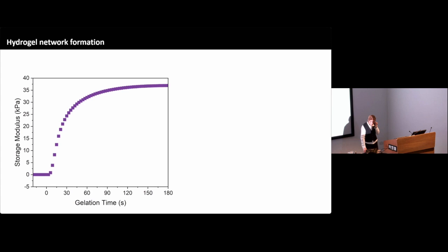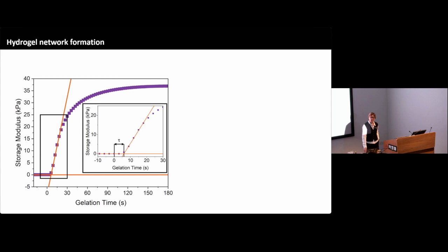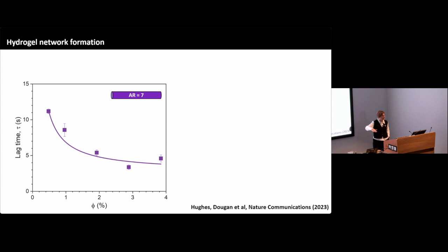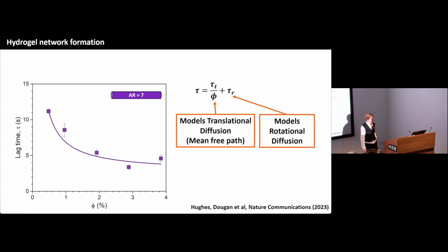And so I'll have to skip over the details, but we did some rheology experiments to measure the storage modulus with time. We measured the lag time, which is defined as the time it takes for gelation to occur. We did this for all of our different constructs and measured the lag time as a function of volume fraction or concentration of our building block in the system. And if you think about that lag time, it's related to how that object is moving around as it tries to form these connections. And there are two components that you consider, the translational diffusion and the rotational diffusion.